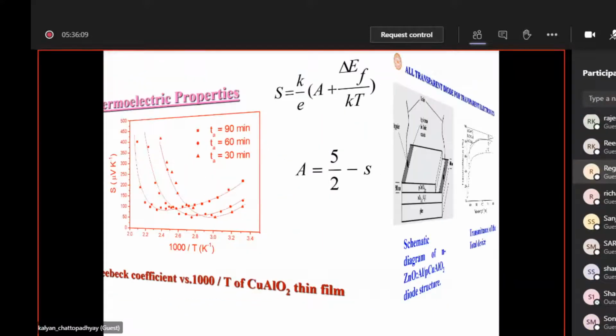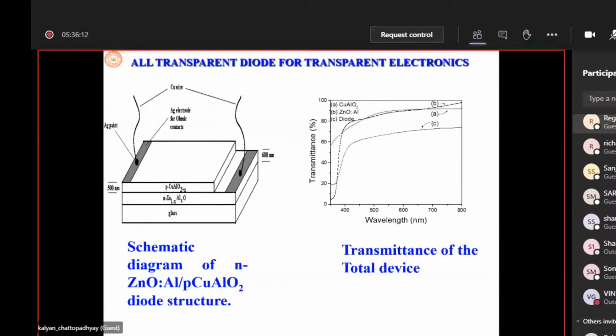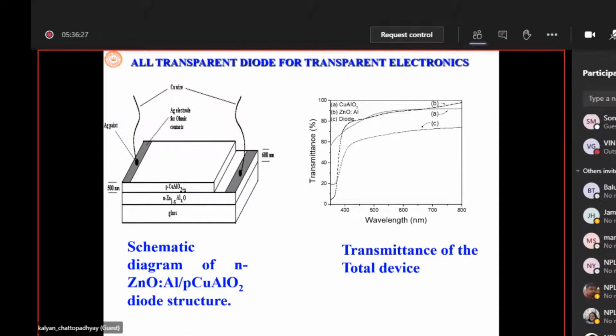Now we also fabricated an all-transparent junction based on doped zinc oxide as the n-type material and oxygen-doped copper aluminum oxide, and the device transparency is more than 80%. We reported this result also.